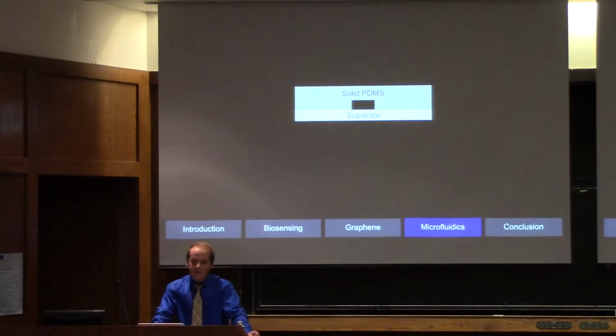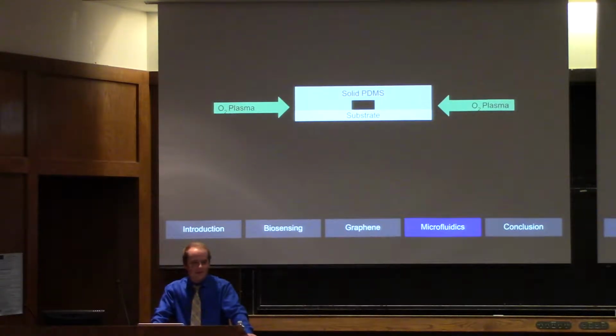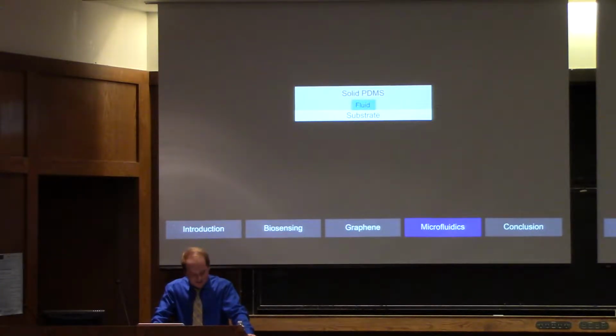At this point, you do a process called O2 plasma etching, which creates a tight seal between the solid PDMS and substrate. In microfluidics, this tight seal is what's most important, because if there's even a little bit of gap between the PDMS and the substrate, the fluid will leak out and it won't go where you want it to, and basically the channel's ruined. So once you have this tight seal, you can introduce the fluid and run your tests.